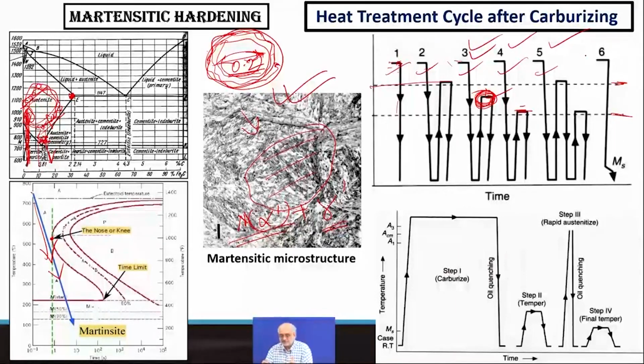So this is a typical single-step carburizing, and this is a two-stage carburizing process, the heat treatment process after carburizing. So we have to understand that the conversion of austenite to martensite requires a special heat treatment after carburizing. In case of gas carburizing or even liquid bath carburizing, it's easier to withdraw and then charge to the quenching bath. But since we have a closed chamber, all these processes are batch processes. So the first part is only carbon enrichment, and the next part is the heat treatment, which essentially is the cycle required for conversion of austenite to martensite. And this is how we can ensure a predominantly martensitic surface in the case or the surface region.